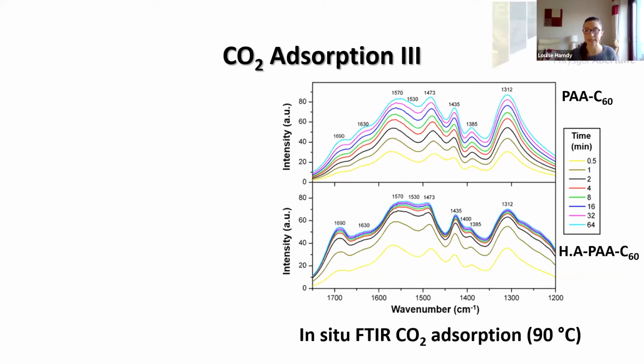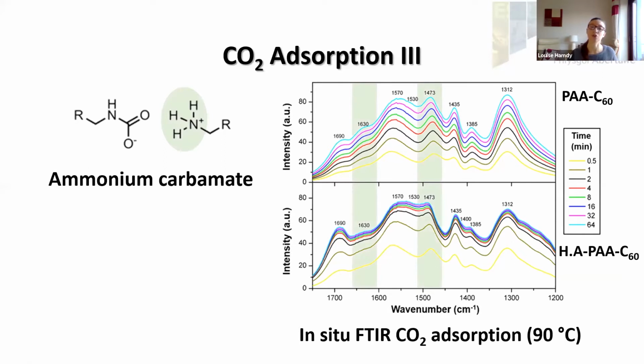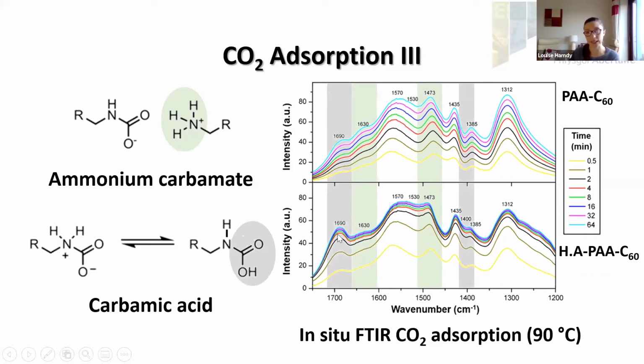So we carried out simultaneous CO2 adsorption at 90 degrees and Fourier transform infrared spectroscopy. And in the spectra, we can see for PAA-C60 and the hydrophobic additive material, the rate of formation of the formed species. And we see that the adsorbed species are formed faster for the hydrophobic additive material. Now, looking at some of the adsorption bands, we can see that there's a bit of a shoulder in PAA-C60 and a peak, which are more pronounced in PAA-C60. These are due to the NH deformation vibrations of ammonium carbamate. Also, there's a peak at 1690 and a bit more of a shoulder at 1400 for the hydrophobic additive material, and this is due to the CO and the OH adsorption bands of carbamic acid.